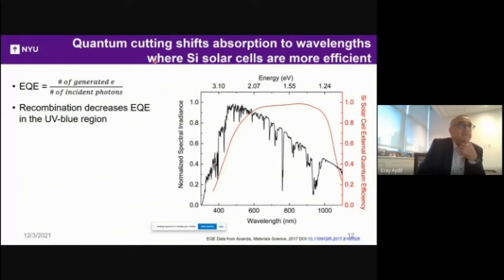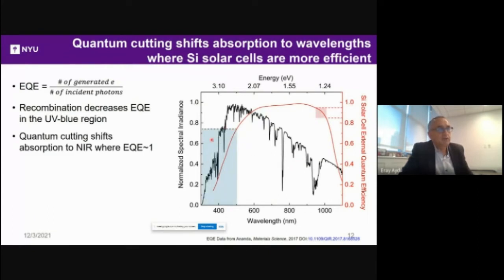But there are also other advantages. One thing is that quantum cutting also shifts absorption to wavelengths where silicon solar cells are more efficient. So this plot shows 2 things. One is the normalized solar spectrum in black, and then also the silicon solar cell external quantum efficiency. So this is the efficiency at which a given wavelength of photons is turned into electrons or current. So if you look in the UV, the efficiencies are decreasing rapidly, right? Going from something like 70% at 500 nanometers down to even less than 20% by the time you get to 300 nanometers. On the other hand, in the near infrared, it's close to 100% or 90%.